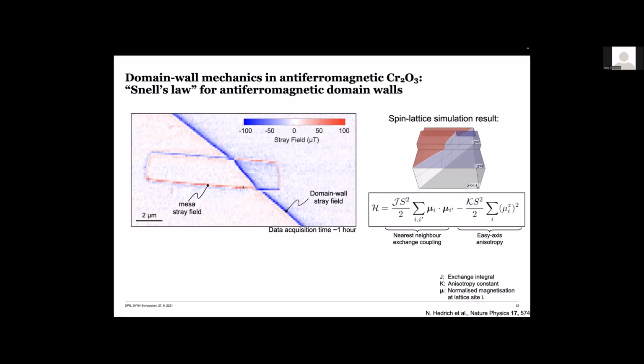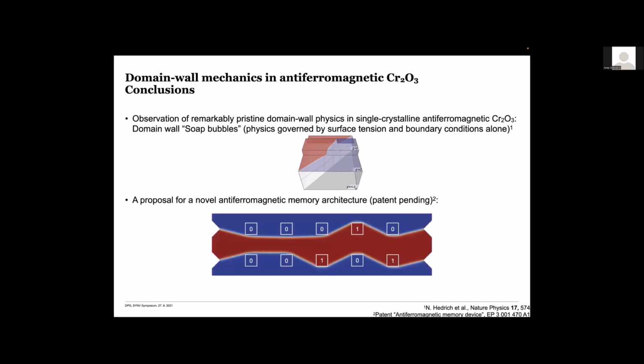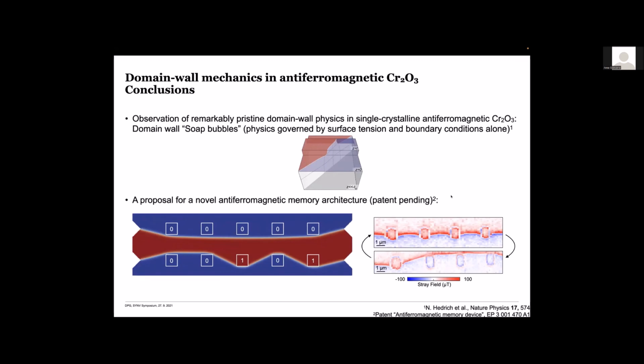Okay, so with this, since I am so late, I'm sorry for that. I want to wrap up. We did push this a bit further, and proposed a new architecture for an antiferromagnet-based memory, which is based on such engineered pinning sites based on such mesas, which could pin domain walls and therefore allow you to encode logical zeros and ones by the path the domain wall takes along such a mesa. We also showed this in first proof of concept.